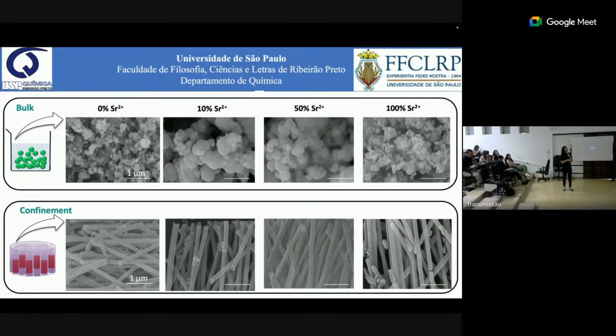And when we used the confined medium, the template, to try to imitate what's happening in vivo, we got this kind of fibrillar mineralized structure. And in the absence of confinement, we got this kind of amorphous structures.